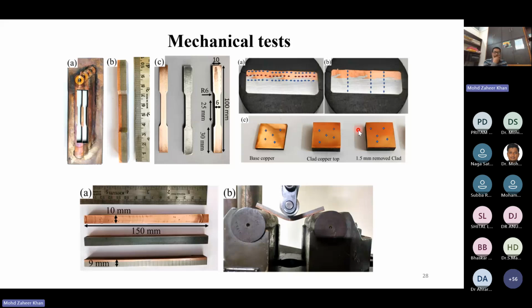Similarly, there is one very important mechanical test that has to be done, and that is to see whether the clad and the substrate materials are peeling off, and that test is known as a bend test. So three types of bend tests were carried out. That is, three specimens were taken out from the cladded layers.